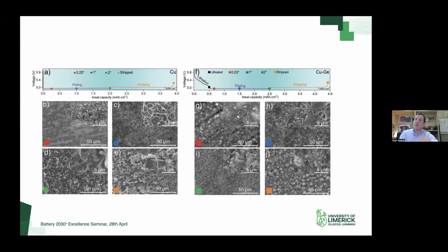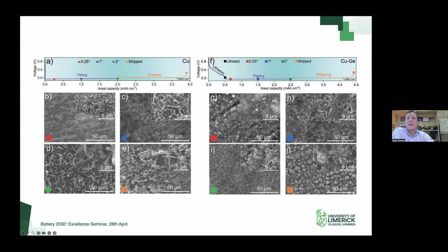So if we look at the ex situ analysis that was done here, on the left-hand side, this is lithium plating and stripping that was done solely in the case of a copper current collector. So you'll see here, this is at 0.25 milliamp hour per centimeter squared. This is at 1, this is at 2. Okay, so again, these are characteristic lithium growth morphologies that we would have seen previously. They're very non-uniform, they're anisotropic. And again, what you can see from the stripping characteristic of these, which were stripped up to about 0.25 volts here, is that you still have residual lithium that is present on the current collector.